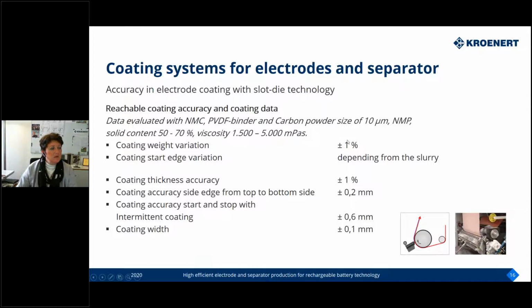So we reached some parameters where we did some tests with a standard NMC material, PVDF binder, and carbon powder in the given parameters. And here we can really guarantee to reach the parameters which you will see here. Coating weight variation plus minus 1%, which is quite good. Also the coating thickness accuracy plus minus 1%. What is also very important for a battery product: on each side you coat the active material, and both sides need to come really edge to edge together, so they need to be at the same position.